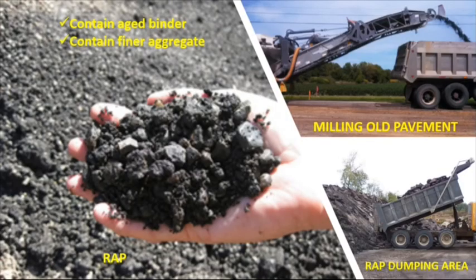This is the photo of RAP, which contains the aged binder and fine aggregate. When planning to use RAP in road construction, there are a few considerations that need to be made. RAP usually contains between 3 to 7% asphalt by weight. In general, the asphalt binder in RAP will be more viscous than virgin asphalt binder due to aging effects. Therefore, if enough RAP is added to the asphalt mixture, a softer virgin asphalt binder should be used to balance the properties of the mix.